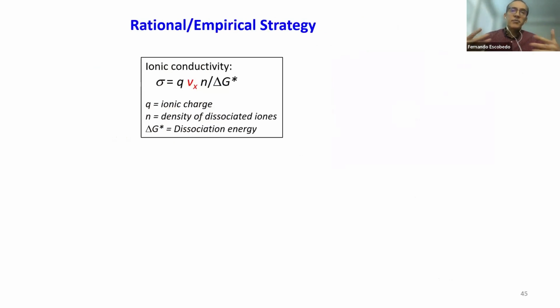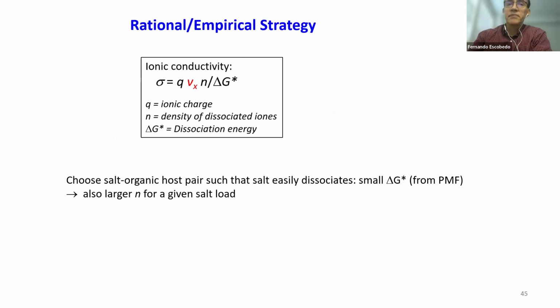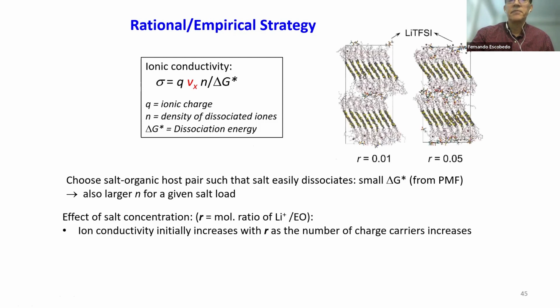Now, this formula already provides a lot of insights as to a rational strategy to try to design these materials. For example, you will try to choose a salt organic host pair such that the salt dissociates easily, right? So you want this delta G to be as small as possible. Also, the more dissociated, for a given concentration of salt, you will have a larger number of dissociated ions, which is what you need for this little n in there. So clearly, that choice is going to be important. We can use similar ideas as before, that you can explore different chemistries and try to identify the ones with the smaller delta G star as suitable candidates for this.